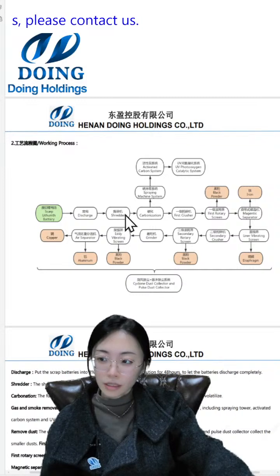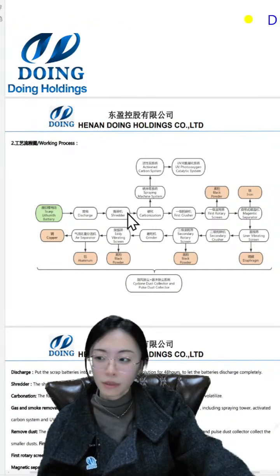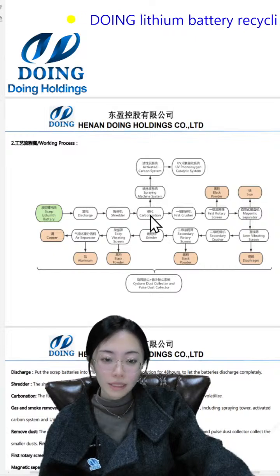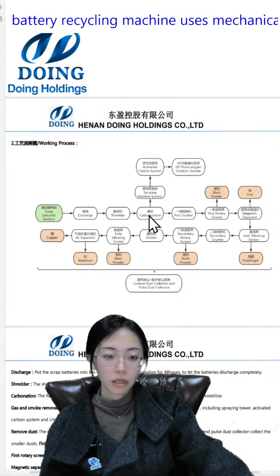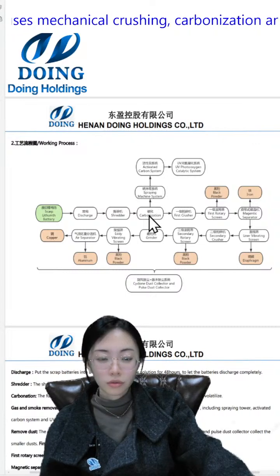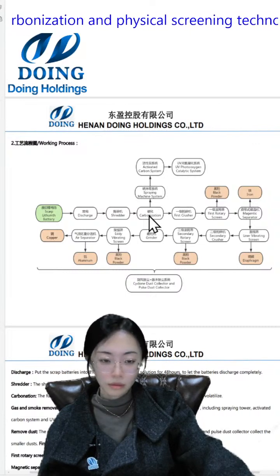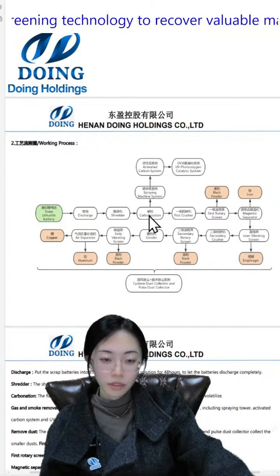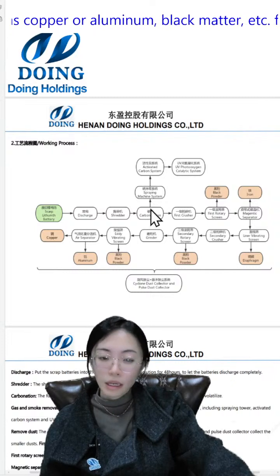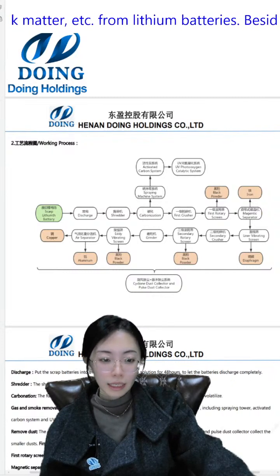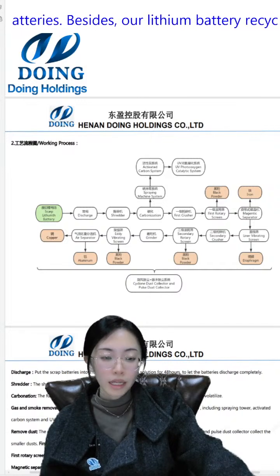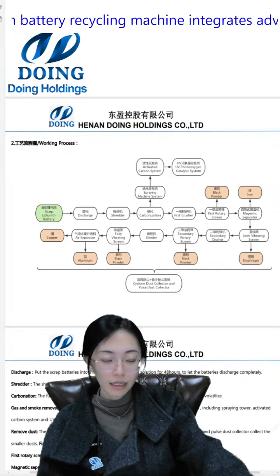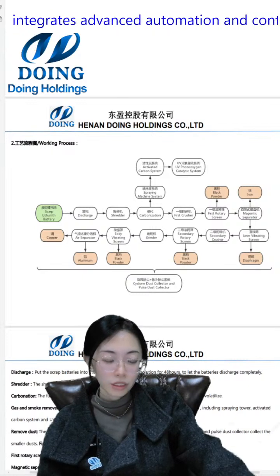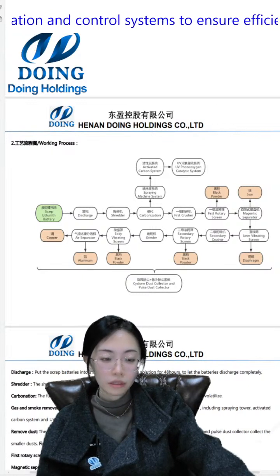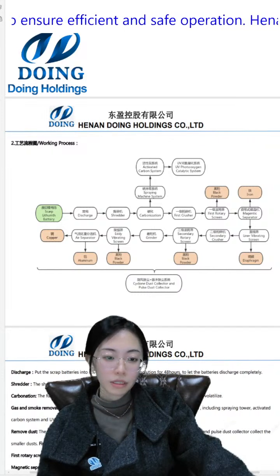So after the scrap crushing step, we can go to the drying step, with the carbonization furnace or the drying furnace, to dry the materials. The moisture of the material should preferably be lower than 15%. Because it has a heating step, the carbonization step, the temperature inside the furnace is nearly 100 to 450 degrees, so the electrolyte inside will just evaporate.